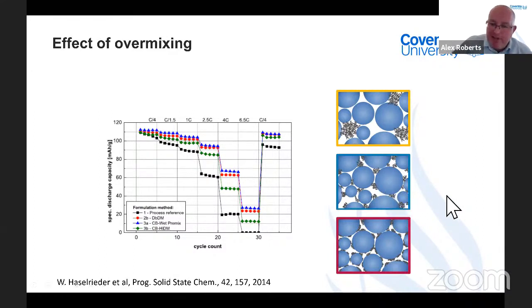If you look at the last image, you can see the situation where you've mixed too much. So if you overmix when you're using something like a carbon black, you can end up coating all of your particles with all of your carbon black and it will not re-agglomerate. So what you find is some particles are connected, but your performance will drop because you don't have the full connection. And you can see this shown in the rate behavior in the graph here going through different mixing technologies.